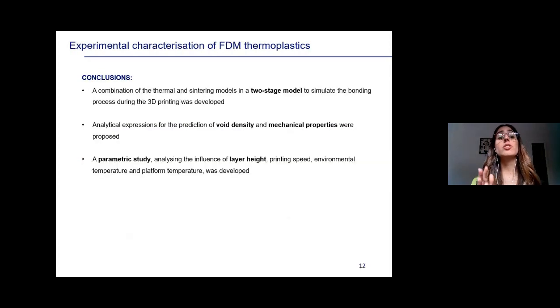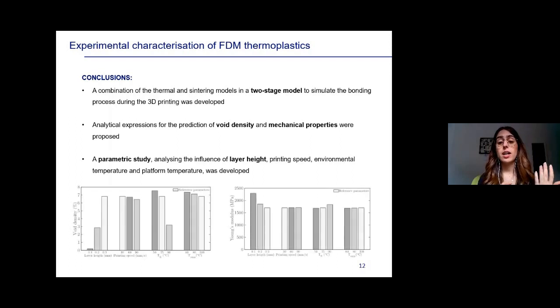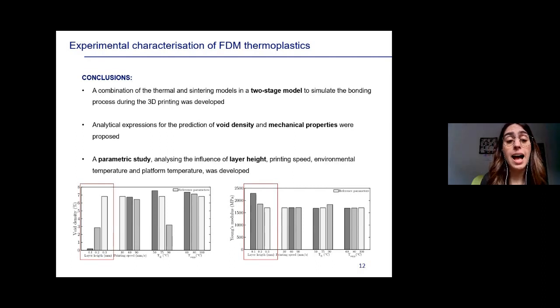So as a conclusion of this second part, we combined thermal and sintering models into a two-stage model to simulate the bonding process during 3D printing. We proposed some analytical expressions for the prediction of the void densities and the mechanical properties, and we used all of them to carry out a parametric study in which we analyzed the influence of different printing parameters such as the layer height, the printing speed, the environmental temperature, and the platform temperature. And I would like to say that from this analysis, we observed that the layer height was the printing parameter with the highest influence on both the void density and the mechanical properties.